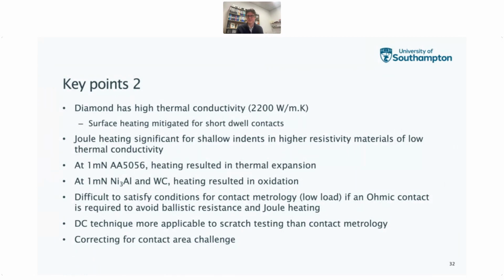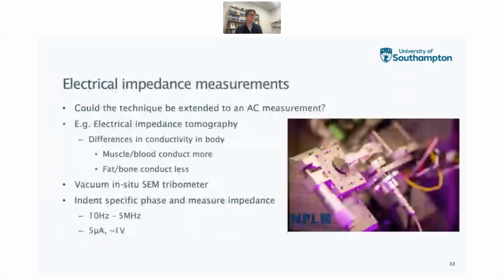It's difficult to satisfy the requirements for contact metrology, where you need this low load, if you actually need an ohmic contact to avoid this ballistic resistance and the ensuing Joule heating that occurs. So we think that perhaps for a DC measurement technique such as this, it might be more applicable for scratch testing, where you have penetration of the material, but the challenge then is to make sure that you have the correct area correlated, and that's something that we're still working on.